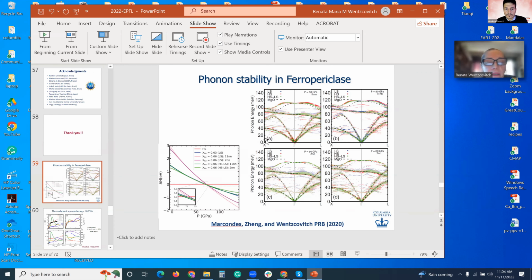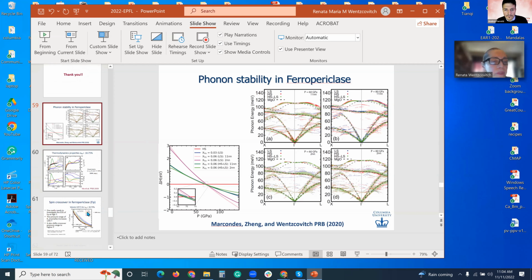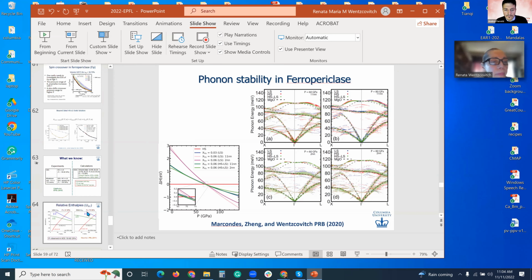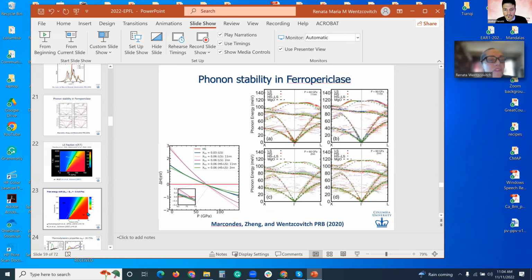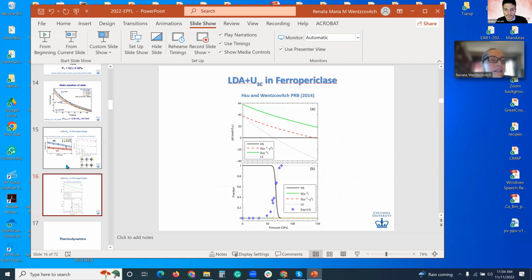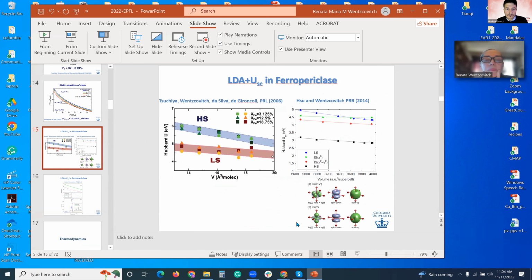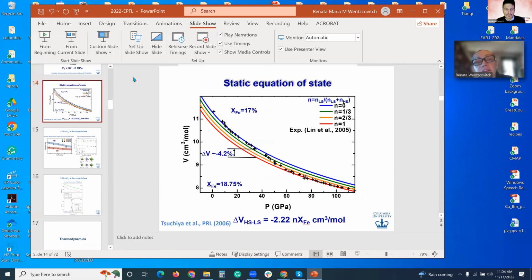Yes, as I said, let me show you. Go back here, perhaps. I think even with the non-self-consistent U, that here, for example, right? Look, U changes upon self-consistence. The high spin U decreases by 3 electron volts. But the compression curve, this is experiment, and this is calculation. Blue high spin, red low spin.